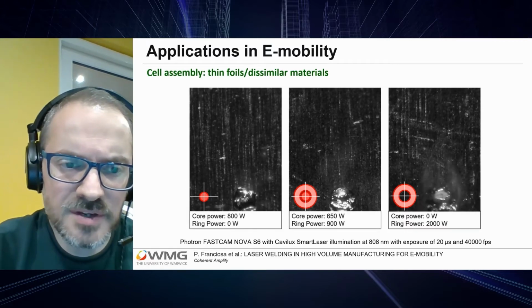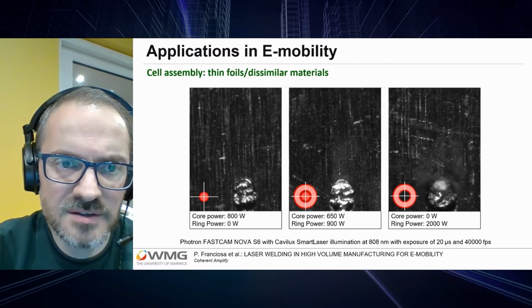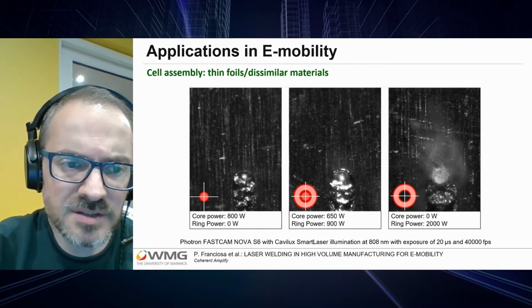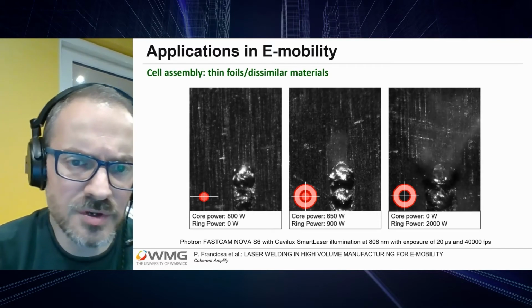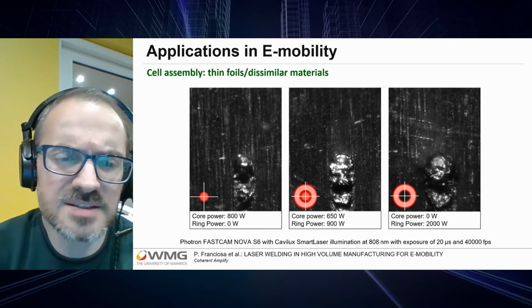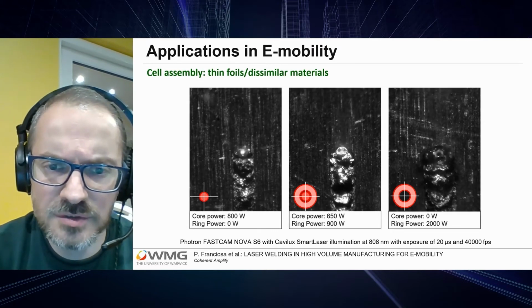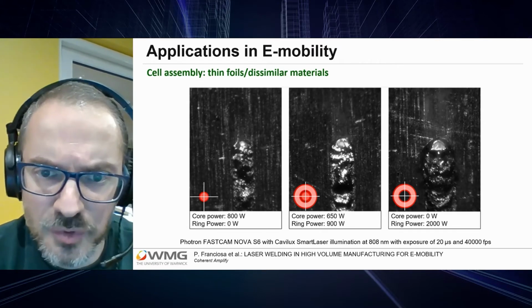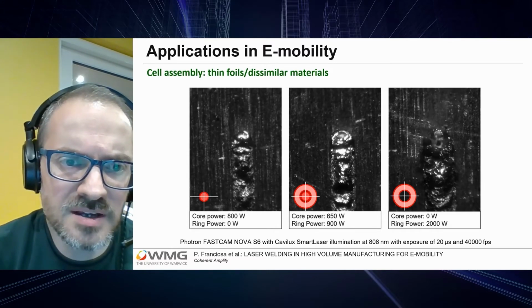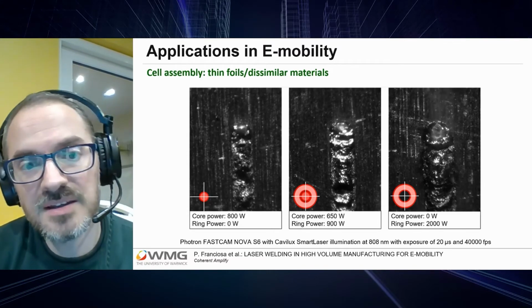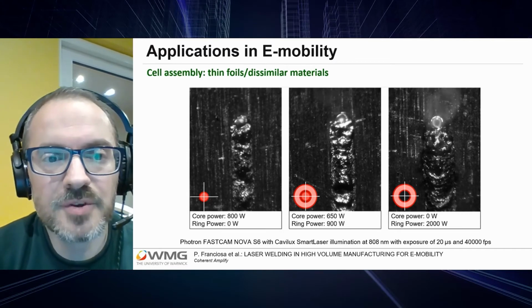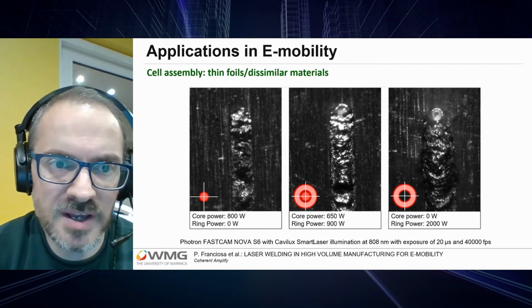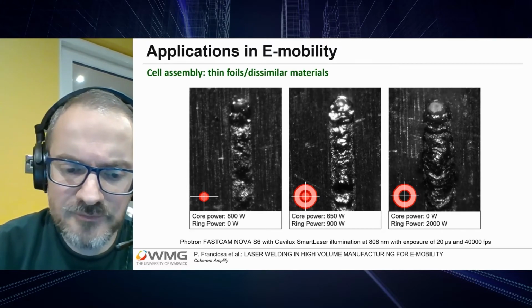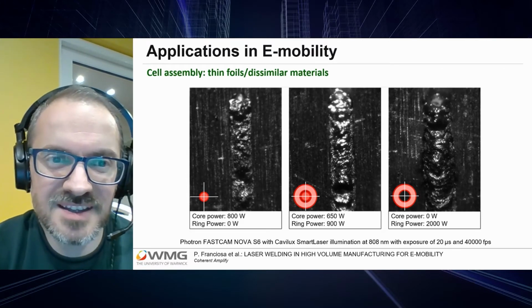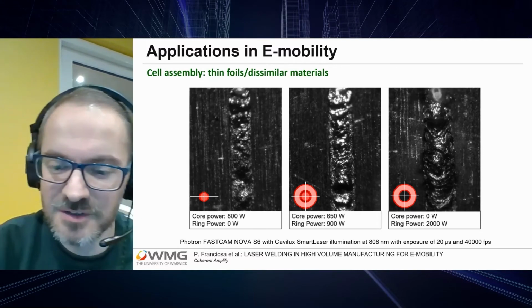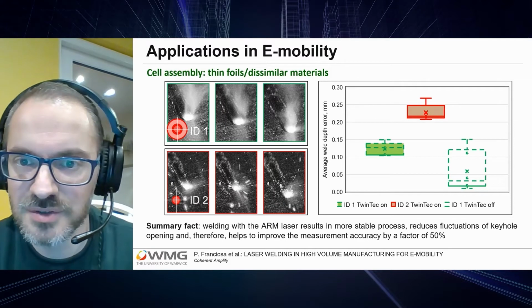And now, if you only focus on the video on the left-hand side and the video in the middle, the video on the left-hand side is the one corresponding to core only. The one in the middle is core plus ring, and we can see clearly that when we use core plus ring, there is a smoother process with a reduction in spatter. And because spatter is most probably related to the instability of the molten pool and instability of the keyhole, we aimed to understand if this is true and if this is reflected within the OCT signal.